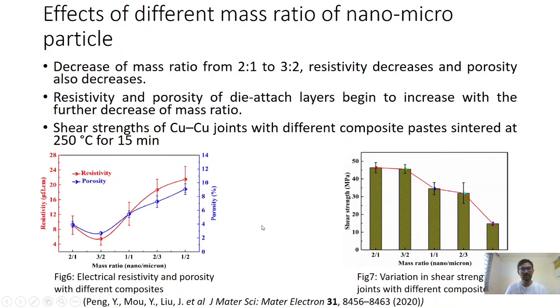The other factor that we will discuss is shear strength. You can see that when the ratio is 2:1, our shear strength is 46 megapascal. When we decrease the ratio from 2:1 to 3:2, our shear strength decreases to 44 megapascal. There is very little change in shear strength, so we can use the 3:2 mass ratio. But if we further reduce our mass ratio to 1:1, there is a very huge change in shear strength. It has decreased to 35 megapascal.